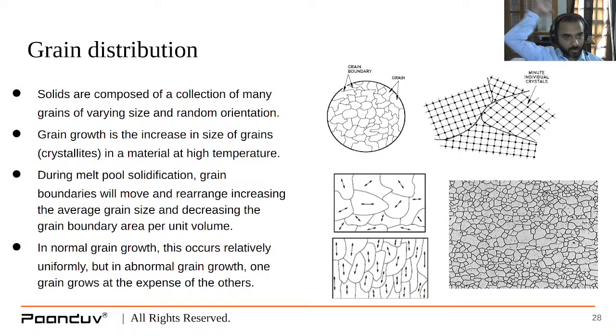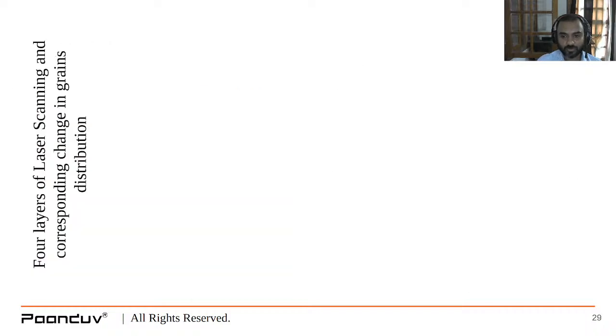On the micro scale side of things, we are interested in grain distribution, where during melt pool solidification grain boundaries move around, they rearrange, they misorient from the supposed-to-be orientation, and the grain size increases or decreases based on the grain boundary area per unit volume, right? In normal grain growth, this occurs relatively uniformly, but in abnormal grain growth, one grain grows at the expense of the other. So one grain will increase in size, the other grains will have to shrink, because the volume has to be conserved, right?